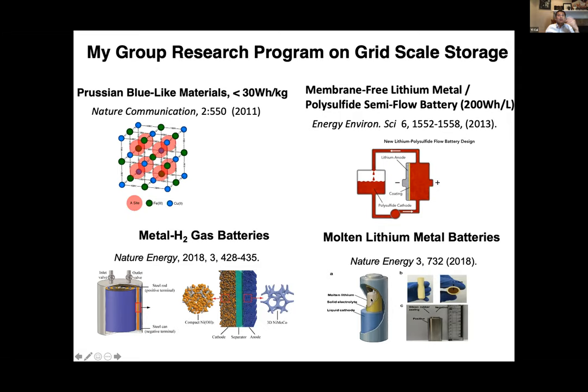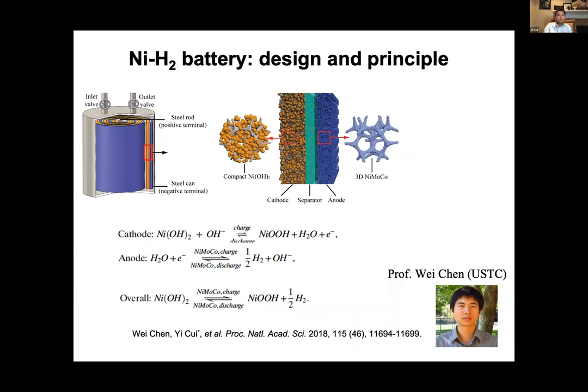In the molten lithium solid-state system, the anode is molten lithium, the cathode is also molten, and the middle layer is solid-state electrolyte. This is analogous to the molten sodium battery using beta-alumina. However, because lithium's melting point is 180°C and lithium-ion solid conductors are much more conductive than sodium ones, this system can operate at only slightly above 200°C — around 240–250°C. The lower temperature makes engineering design much more convenient. For metal-hydrogen gas batteries, which we have been demonstrating in the past few years: the cathode is nickel hydroxide / nickel oxyhydroxide — a chemistry that can go up to 100,000 cycles. The anode is hydrogen converting to water and back — half of a fuel cell.